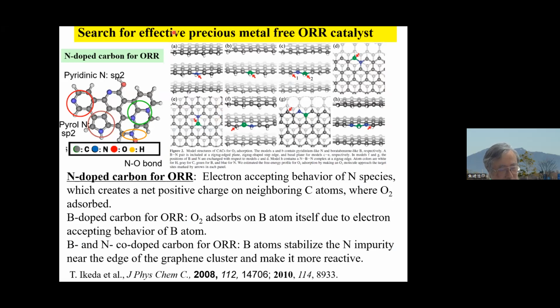Of course, many people have been studying this, and one of the candidates was nitrogen-doped carbon for the oxygen reduction reaction. Many people carried out research theoretically or experimentally. In the case of nitrogen-doped carbon, the electron-accepting behavior of nitrogen species makes a net positive charge on neighboring carbon atoms, where oxygen is adsorbed. Of course, oxygen must be adsorbed first as the first step. So nitrogen doping is good, but boron-doped carbon is also good. In the case of boron-doped carbon, oxygen is adsorbed on the boron atom itself.